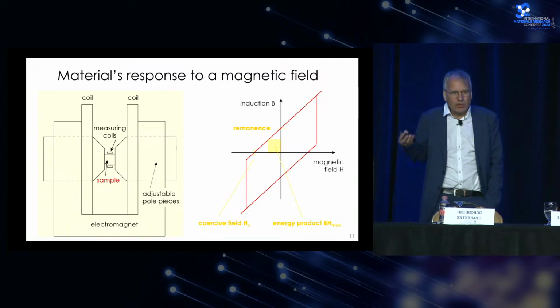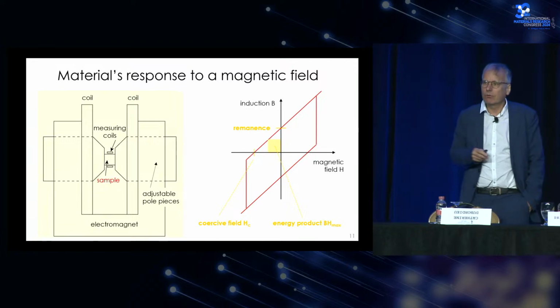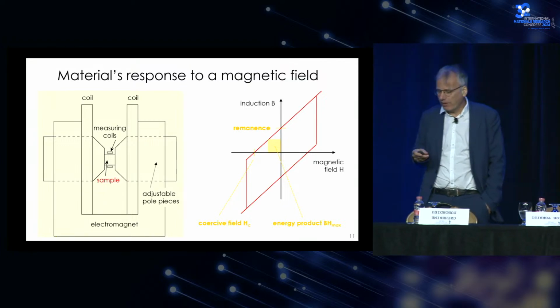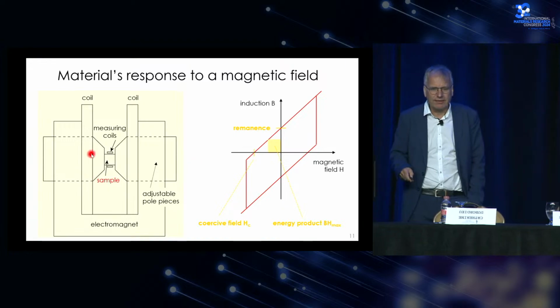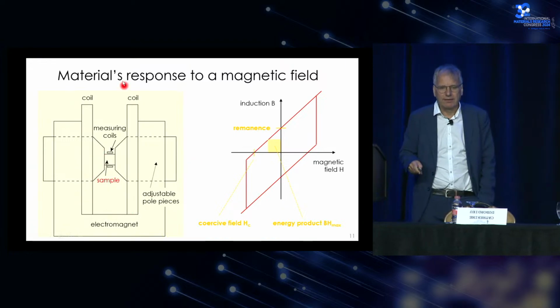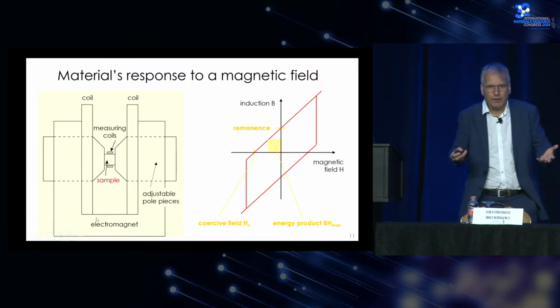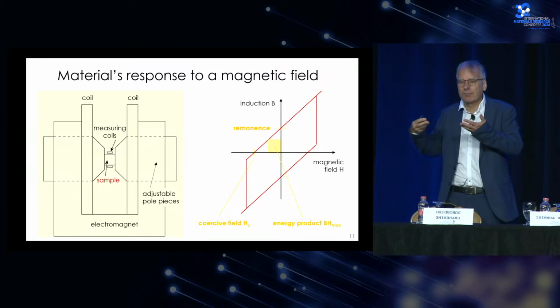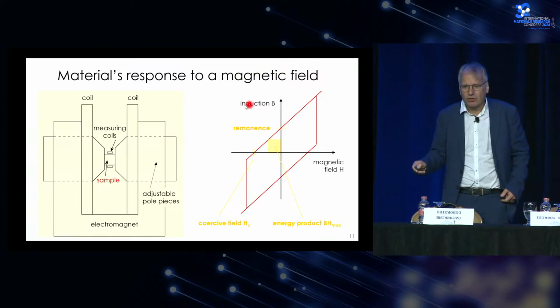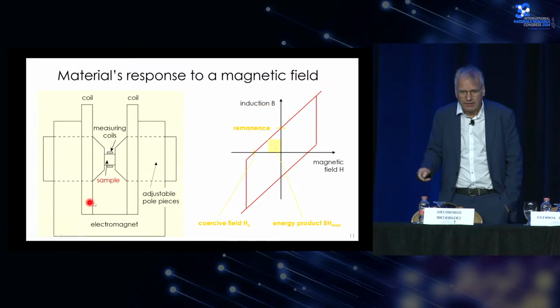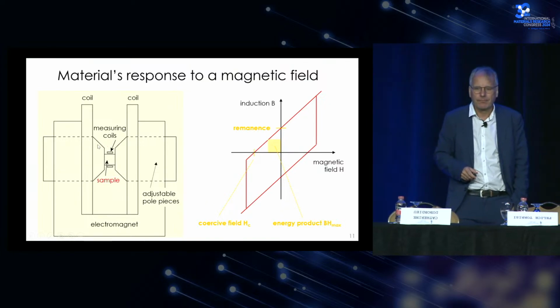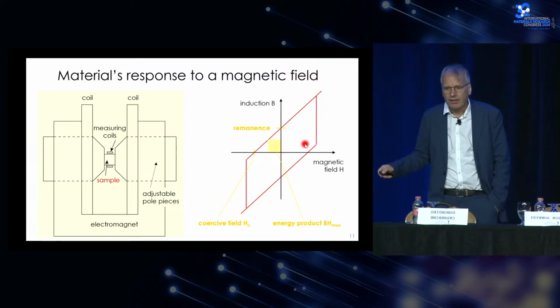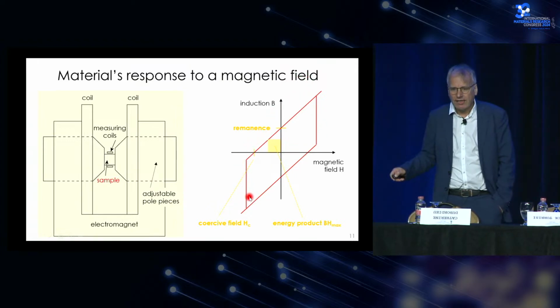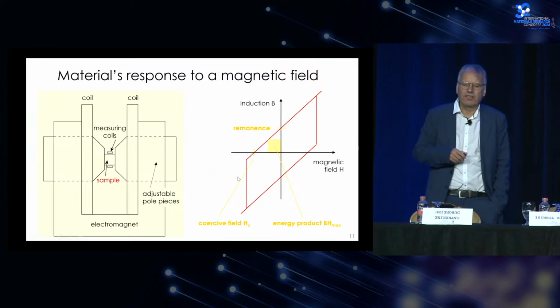How do we measure the properties of the magnet, and what are the most important properties of a magnet? Normally you measure the properties of a magnet by putting the sample into an electromagnet. The electromagnet creates a field, and the magnet responds with a magnetic induction or magnetic flux. This magnetic induction is measured by these measuring coils around the magnetic sample. If we do the measurement, then we can plot the magnetic induction as a function of the magnetic field. You can see a typical ideal hysteresis curve here.